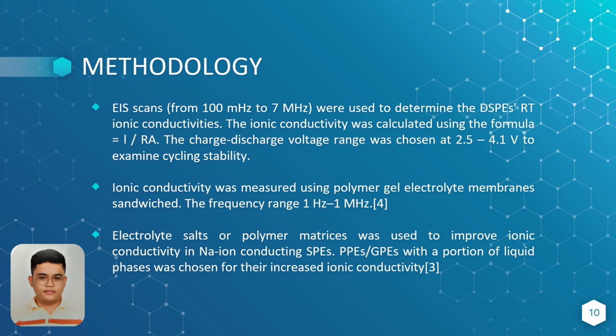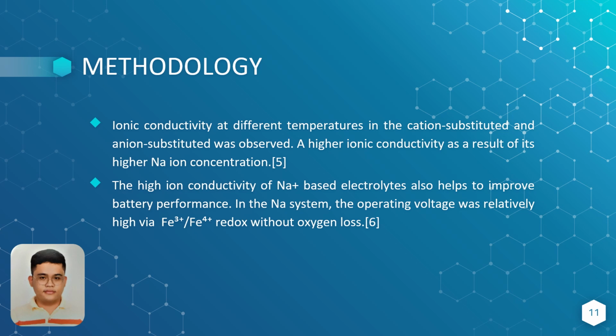ionic conductivity. There is also another methodology where the ionic conductivity at different temperatures in the cation-substituted and anion-substituted materials was observed. A higher ionic conductivity was found as a result of its higher sodium ion concentration and larger unit cell. The last method is when a similar sodium or vacancy chemical composition is formed. The P2-type layered material has a higher ionic conductivity than the O3-type layered material.